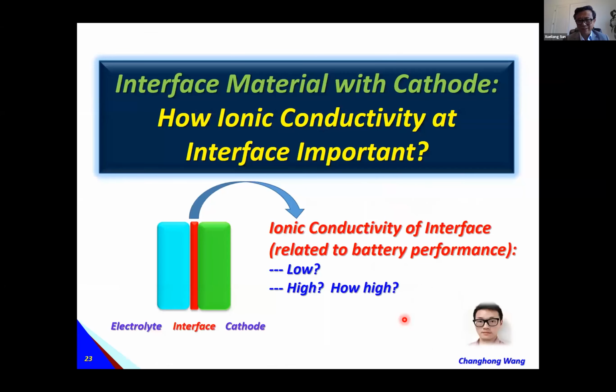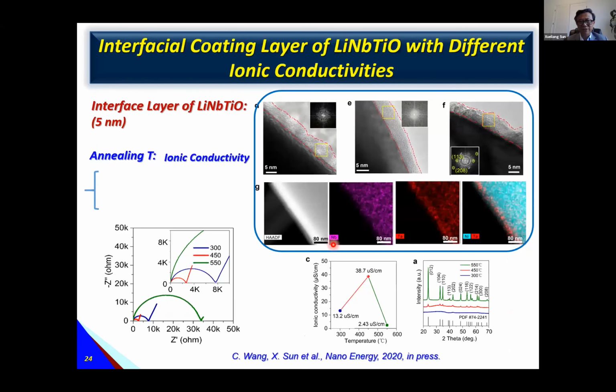So after this, I just show you one more example here: how important the interface is in terms of ionic conductivity. Is it low or high? How high is good? In order to answer this question, we have lithium niobium titanium oxide, with the interface maintained at 5 nanometers with different annealing temperatures. We can control different ionic conductivity. At 450, we can maintain the highest ionic conductivity.